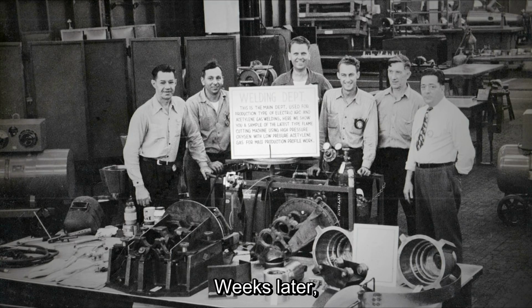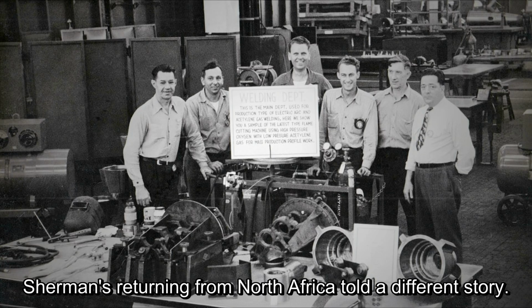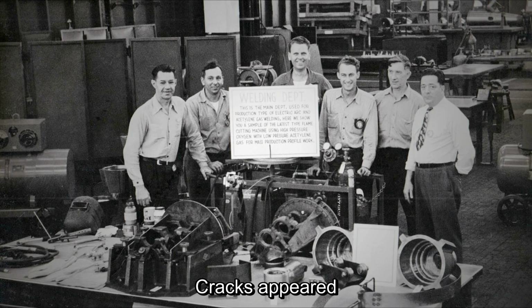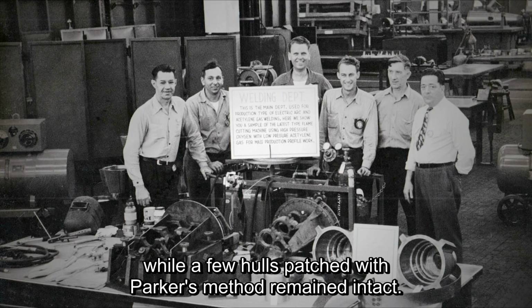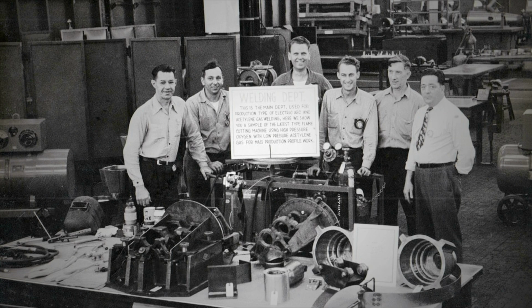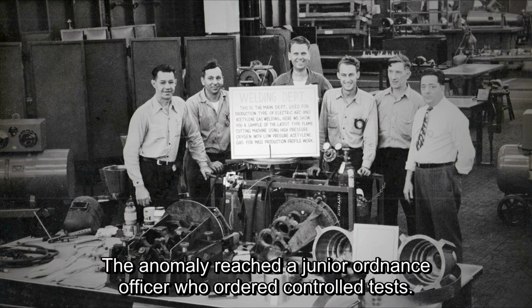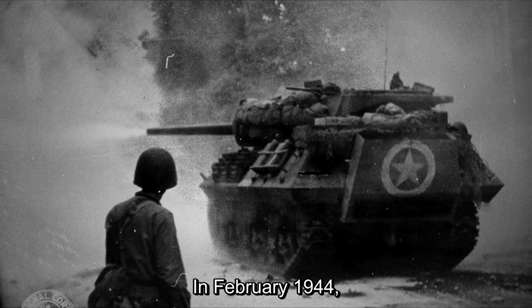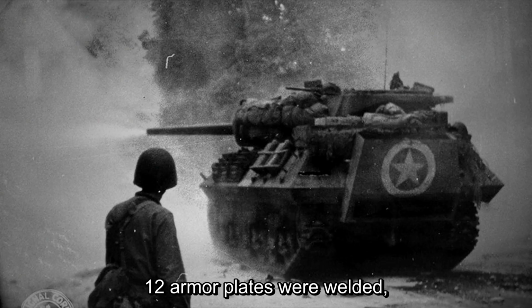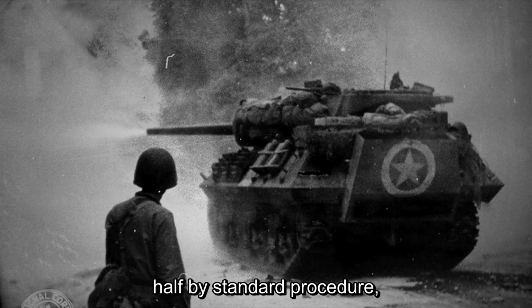Weeks later, Shermans returning from North Africa told a different story. Cracks appeared along perfect horizontal seams, while a few hulls patched with Parker's method remained intact. The anomaly reached a junior ordnance officer who ordered controlled tests. In February 1944, at Depot No. 3 near Chester, 12 armor plates were welded, half by standard procedure, half inverted.